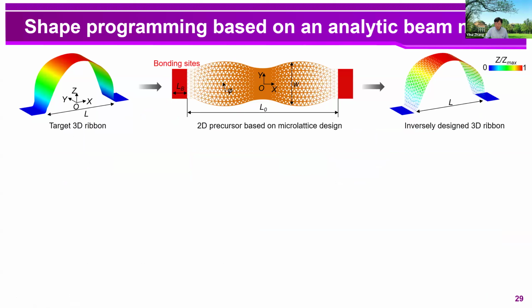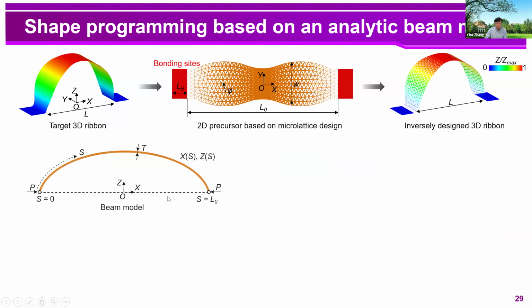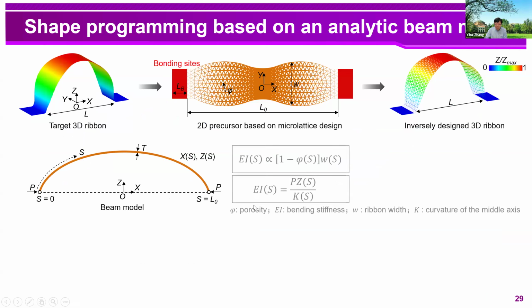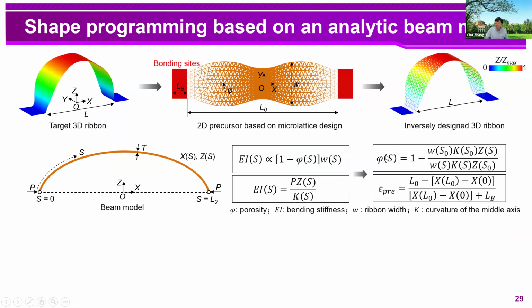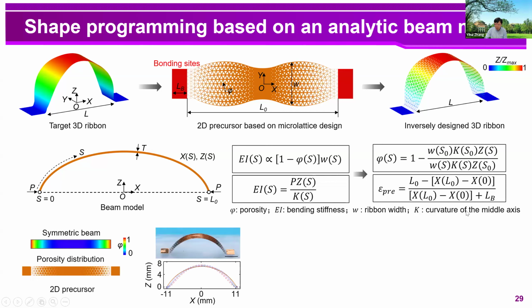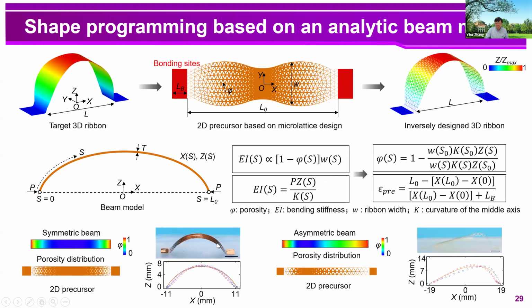Then we look at the regional inverse design of the shape programming. And in terms of the straight ribbon structure, the inverse design problem is actually to find an optimal porosity distribution of the 2D precursor that can yield the assembled 3D ribbon, which agrees very well with our design target. So in the condition of simply supported beam, we can derive this kind of analytical solution of the porosity distribution in terms of the curvature distribution and the width distribution. And if you look at the results here, you will see that the analytical solution agrees very well with our experimental results for arc-shaped ribbon structures.